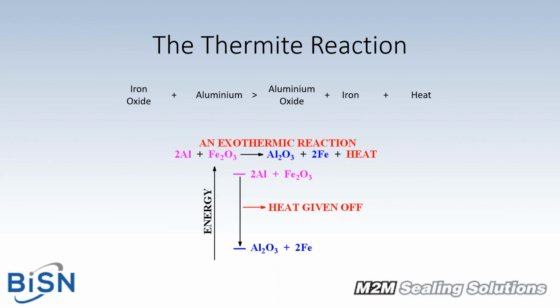With the thermite reaction, we get an awful lot of heat. It's a non-explosive chemical reaction between iron oxide, rust, and aluminium powder. You put the two together in the right quantities, with the right grain size, etc. Heat it up to about 2000 degrees C. It starts a chemical reaction which produces liquid iron, heat, and aluminium oxide, and we use that heat to melt